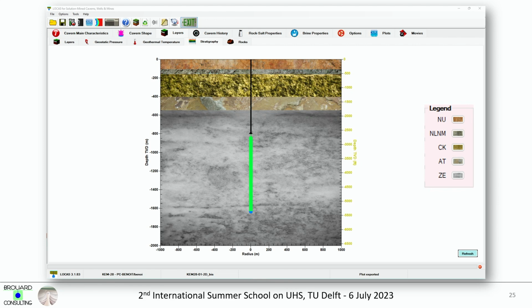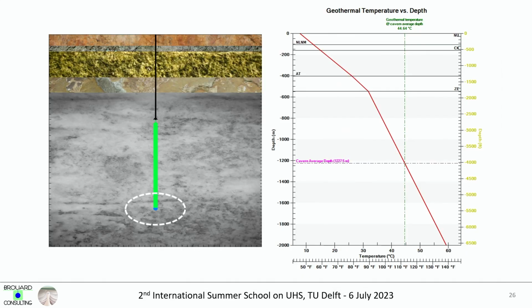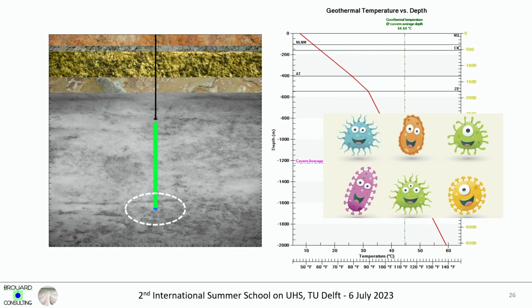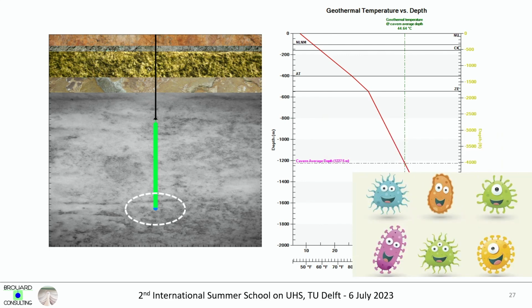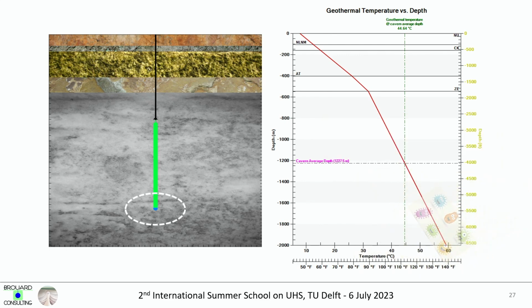in Germany, a kind of cylindrical cavern, which could be very deep. You know that the deeper you go, the higher the temperatures you get, and that's relevant for microbes, because we can get microbes at maybe 60, 70, 80 Celsius, but if it's deeper, the microbes can disappear. So it's good to have a kind of elongated cavern with a quite deep bottom, because you probably have less risk with the microbes.